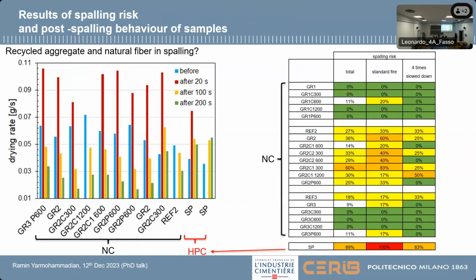As you see, after the spalling, now we have two new exposed surfaces. And when we are dealing with normal concrete, we have a reduction in the drying rate. So the two new surfaces are gonna dry easily and fast, and there is no more water there. While in the spalling-sensitive or high-performance concrete, we still have high moisture which is kept there. And that's one of the reasons that high-performance concrete is very sensitive to spalling.